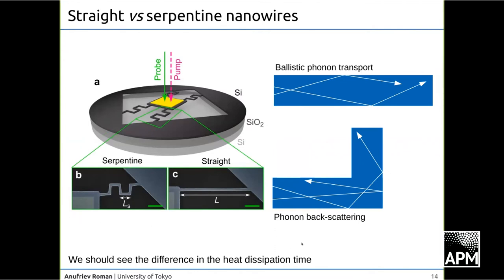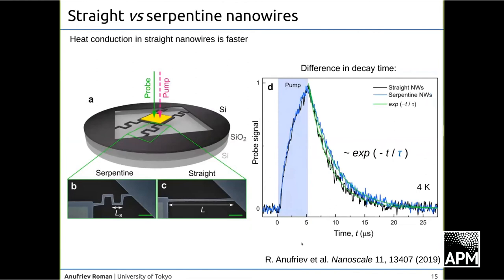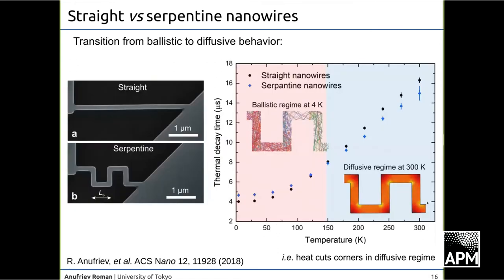Then we measured the heat dissipation time. Remember I introduced this tau constant, how quickly heat dissipates through these wires. We can see that if we take a straight wire, heat dissipates along the black curve, which is faster than the serpentine curve, which is blue. In other words, through the straight wire, phonons can escape faster than from the bent wire, presumably because there are turns which scatter the phonons backward. Yes, so this is at 4K, but what happens if we increase the temperature?